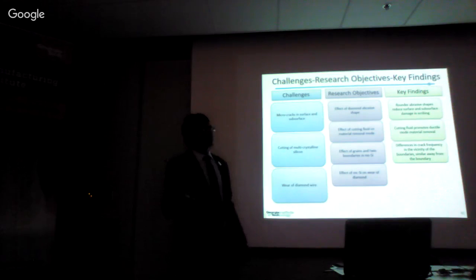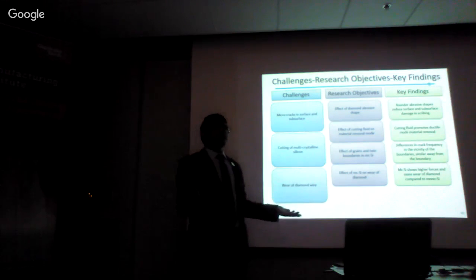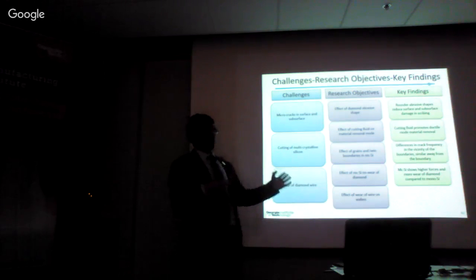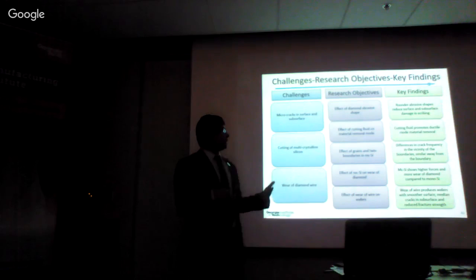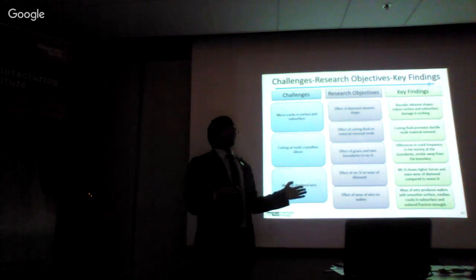And the last challenge which we addressed was about the wear of diamond wire. And this was related to cutting multi-crystalline silicon, that there was greater consumption of the diamond wire while cutting multi-crystalline silicon compared to monocrystalline silicon. And we found that multi-crystalline silicon shows higher forces and more wear of the diamond overall compared to scribing of monocrystalline silicon. And to address another challenge about the effect of wear of diamond wire on the silicon wafer surface and subsurface damage, we find that with wear, we have a smoother surface, but median cracks in subsurface, which reduces the fracture strength of these wafers.